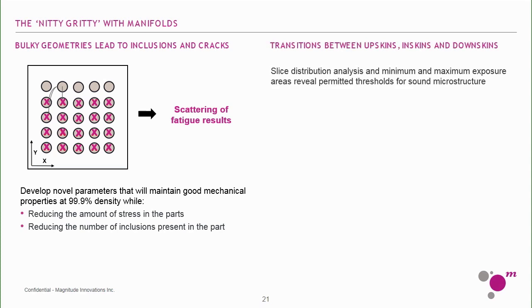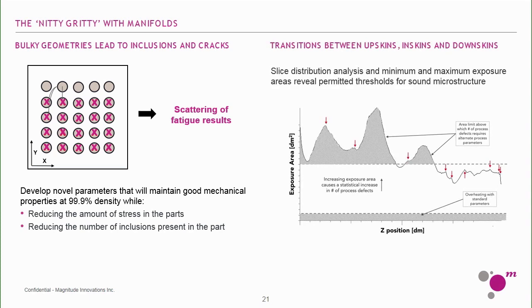Now, when we did that, we first took a look at the actual distribution of the geometry. So when you take a look at a simple graph like this, we first try to analyze this little area where, when the exposed area per layer is very small, the material overheats. Titanium specifically is extremely sensitive to that, because if you have a laser pass that is a little bit off and overlaps with something that was done previously, the material begins to boil and you have porosity. So we have to be very careful to make sure that the exposure area between layers is significant, so that you will not get to this lower point of boiling. Then you have this sweet spot where it's shown in the white.